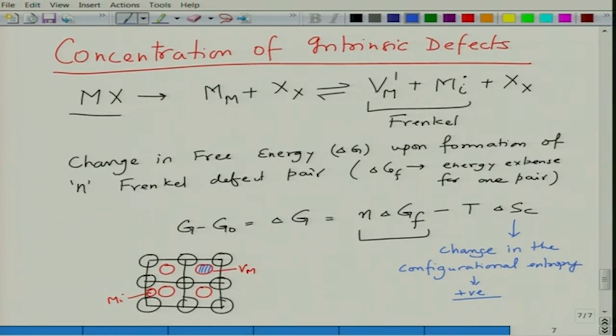So, basically the equilibrium concentration of defects, this small n, will have a certain finite value only if the free energy is negative at that point. There has to be free energy minimization, which means we would like to minimize this free energy with respect to n, to find out the value of n at which free energy is minimum. So, we need to do certain things.